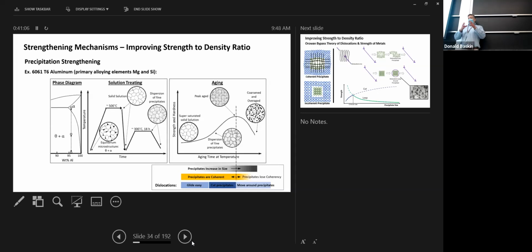And you take these materials, you heat them up to some temperature that's shown here, 500 degrees Celsius, and all those atoms diffuse and they're moving around in there with all the other atoms. And then if you take that material and quench it, they kind of get locked in position. And with time, what will happen is those atoms will diffuse together and make little precipitates. They start off really small, like a nanometer size. And then with time or temperature, they'll grow a little bit. And then there's some optimum size that gives you the highest strength. That's here. This is aging time versus strength.